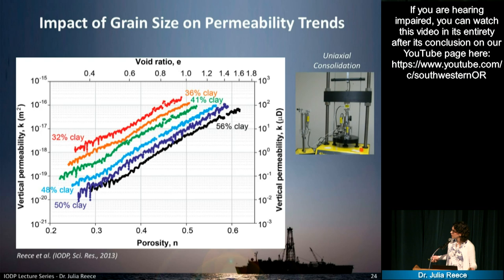If you look at just one particular porosity, let's pick 40%, or 0.4 here, and we go up, we see that since this is on a logarithmic scale, there's actually two orders of magnitude difference in the permeability at one given porosity for a change in the grain size that is about 24%. And you might be like, oh yeah, what does this mean? But these are parameters that people often use in large-scale models and basin models to understand how the basin evolved as time, pressure, and temperature went on.